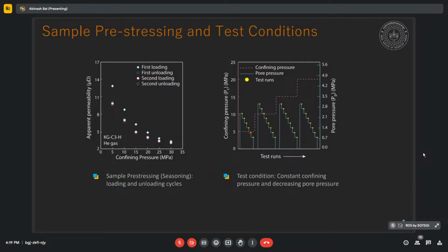In our case, we kept the confining pressure constant. The pink color is for confining pressure, and we decreased the pore pressure stepwise. That means we kept the pore pressure here, measured a permeability, then decreased it, then again measured. Why have we done this? Because a reservoir is generally located at a particular depth, corresponding to a particular overburden pressure, and that overburden pressure stays constant. At that overburden pressure, we continuously excavate oil and gas, and the pressure of the reservoir decreases. To simulate that, we followed these test conditions in the experiment.